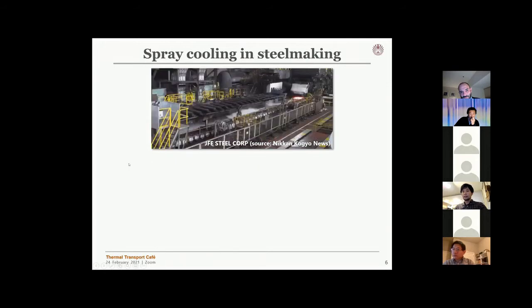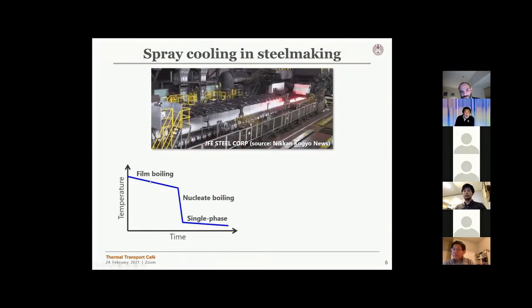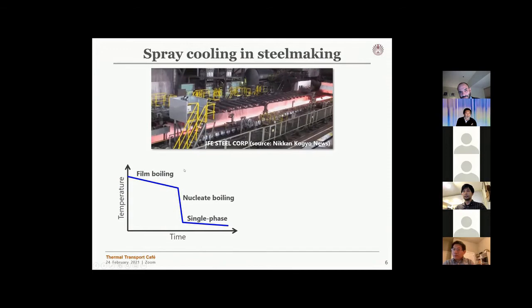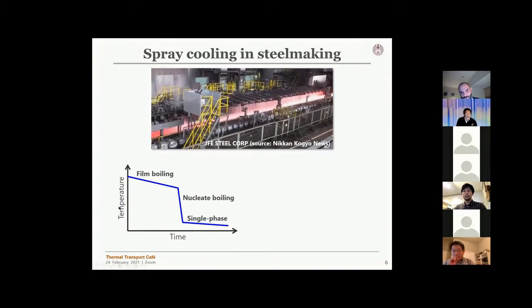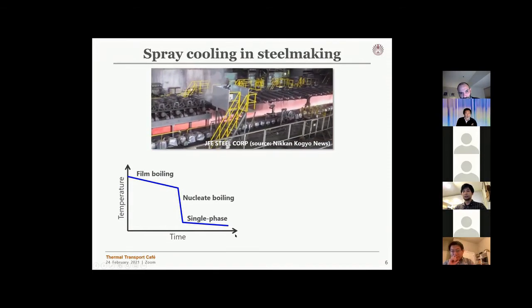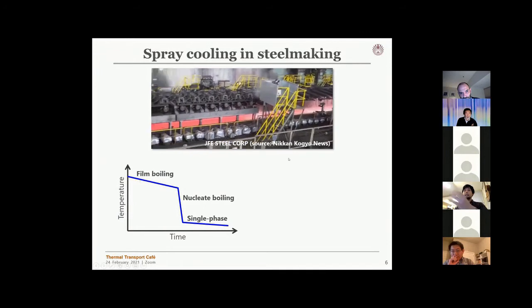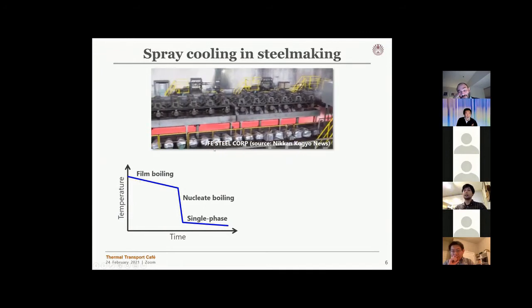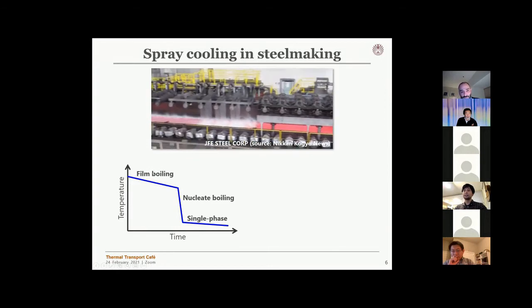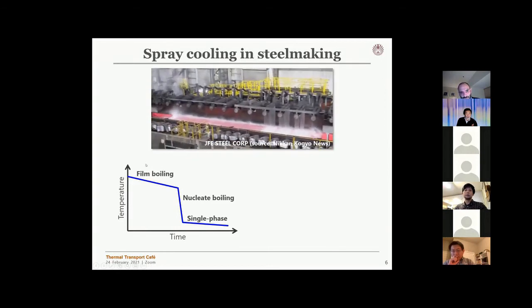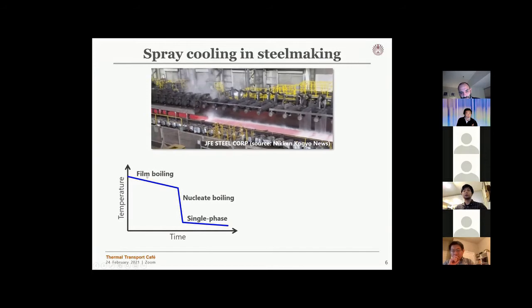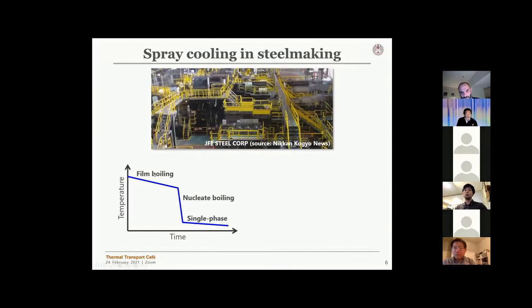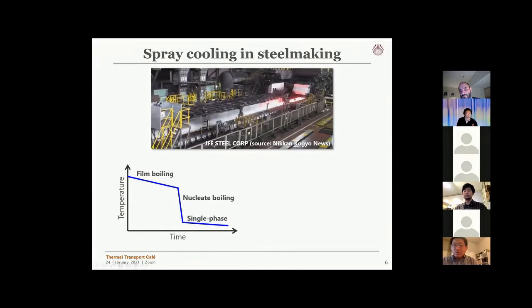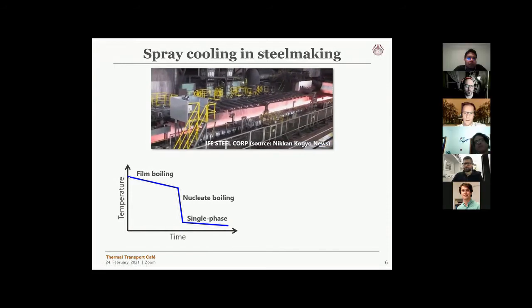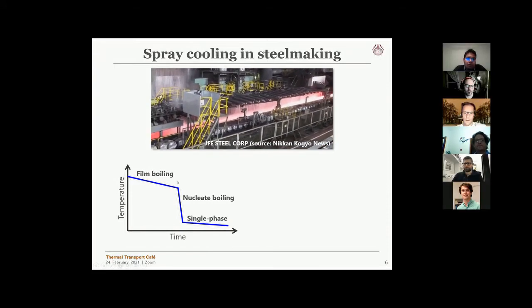This chart shows a typical cooling profile of this spray cooling process. If you take the temperature of the material as a function of time, since the temperature of the plate is around 1000 degrees Celsius, you obviously start with the film boiling regime. Film boiling regime generally has poor heat transfer performance, so the temperature decreases like this.